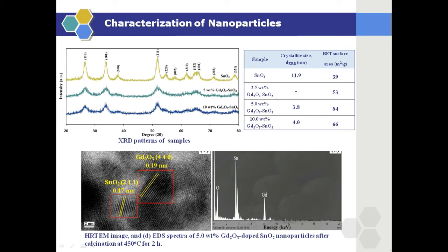Since the ionic radius of Gd is much larger than that of Sn, all added Gd ions may not fit within the tin oxide crystal lattice due to its excessive distortion. As you can see the high-resolution TEM result, Gd in excess of its solubility can place between tin oxide grains and prevent the growth of tin oxide crystallites. This trend continues until the dopant fulfills all of the grain boundaries.